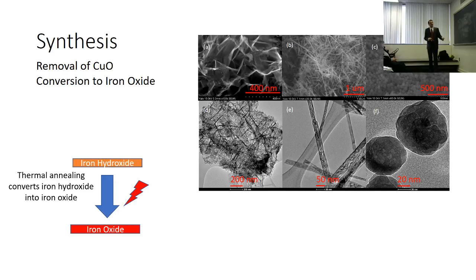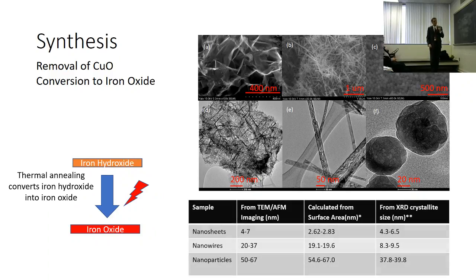So I did that. Had some nice, by themselves, hematite nanosheets. They were polycrystalline, pretty thin, about 4 to 7 nanometers by AFM. I wanted to compare in this work how they look compared to other dimensions of hematite, like nanowires and nanoparticles. So I got some collaborators, Julie Zimmerman's lab. Amanda gave me some very nice nanoparticles, and Julian made some very good hematite nanowires and optimized the nanosheet synthesis. And we were all set.